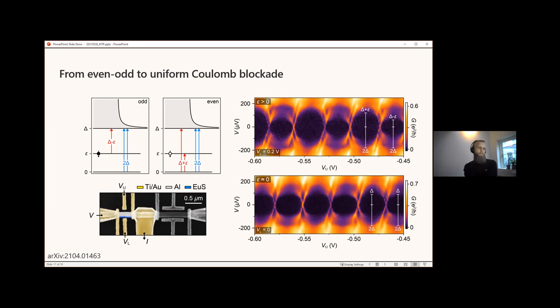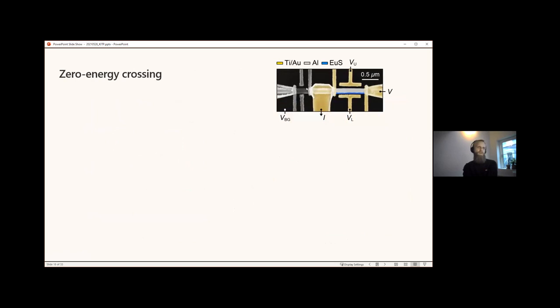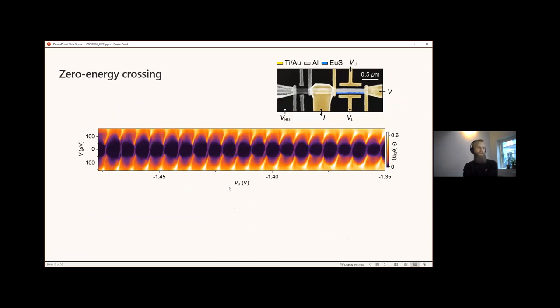We can also look at the longer island. That one was 400 nanometers. We are now moving on to 800 nanometers. And we can also look at bigger ranges of the gate voltages. In this case, the upper gate voltage on the aluminum side tunes the occupancy of the island. And we see the Coulomb blockade evolves from even-odd through 1e to even-odd again. To help you look at these Coulomb features, I am going to draw some lines here. Then we can define these Coulomb steps as the following excitation energies.